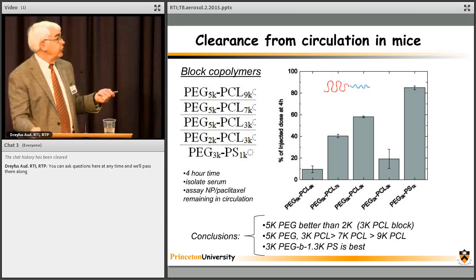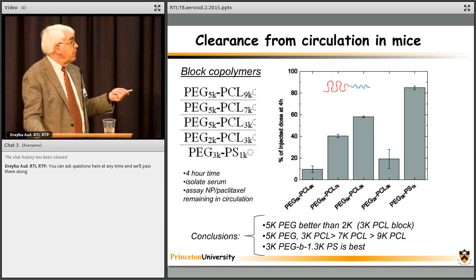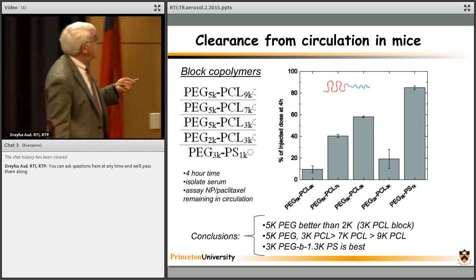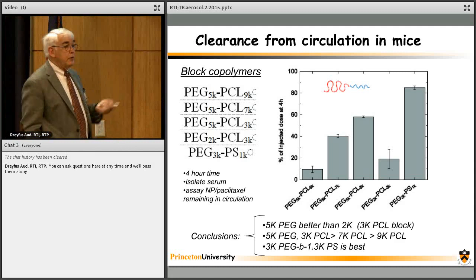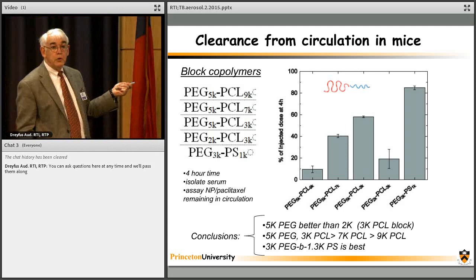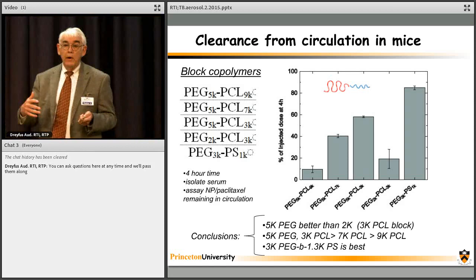But now let's look at the molecular weight of that polycaprolactone block. So this now goes from 3K, 7K, 9K. And you think, well, isn't the bigger hydrophobic block better? And the answer is no. What we see is the bigger hydrophobic block clears much more rapidly. And the 3K is best. Now, you can't go below 3K because then the anchoring energy isn't great enough for it to stay locked on the surface. But why is the bigger hydrophobe worse?